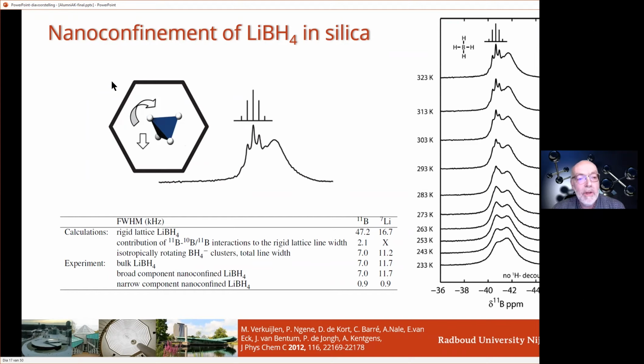So we started to look, and as I said, the nice thing of NMR is that we can look at the entire periodic system. And here we see some boron spectra as a function of temperature. Even at ambient temperatures, we see that there are two overlapping peaks. And one of these peaks even develops some fine structure. I chose this example because three important NMR interactions are present in this spectrum, which helped us figure out what happens to lithium boron hydride nano-confined in silica pores.